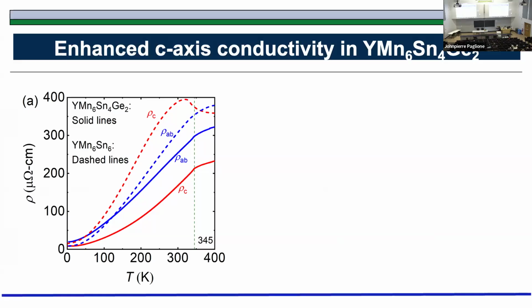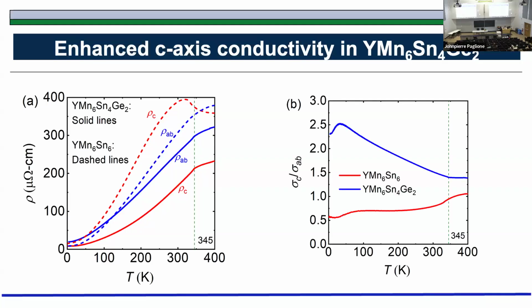And it's telling us probably something about its electronic structure, looking at it here, because what happens now, see the switching of this thing? The red one is on top of the blue one here, and that switches here. So somehow when you put germanium into it, the electrons find it easier to move perpendicular to the layer, unusually, right? Than moving in this direction. So that is one clue for us to see that, okay, it might have changed something electronically, although this is the isostructural dope, right? And then this is basically just the ratio of the C-axis conductivity over AB plane conductivity, and this is smaller in the parent compound and large in the doped compound. So C-axis conductivity is enhanced, basically, the theme is.